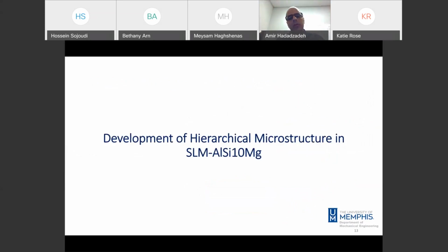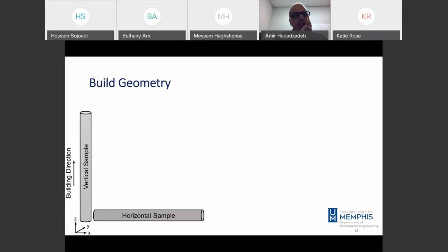So I start with a case study here about development of hierarchical microstructure in SLM AlSi10Mg. AlSi10Mg is the most common aluminum alloy used for selective laser melting, because the composition of this alloy is close to the eutectic composition of the aluminum-silicon system. So we have a narrow range of solidification, which is pretty helpful in terms of making a component without any significant defect.